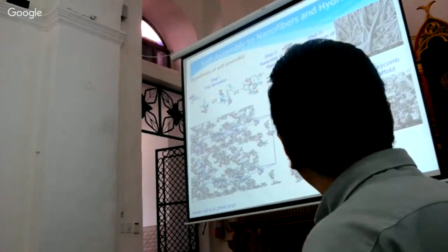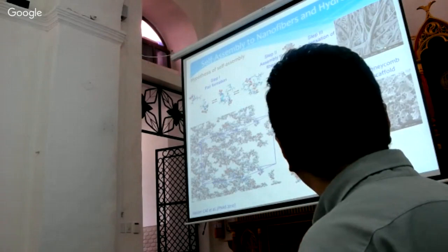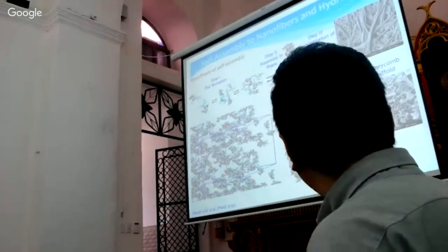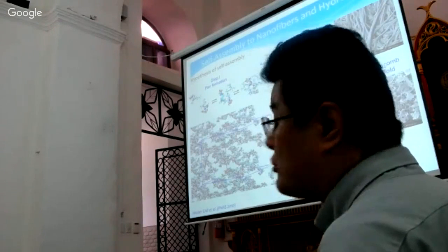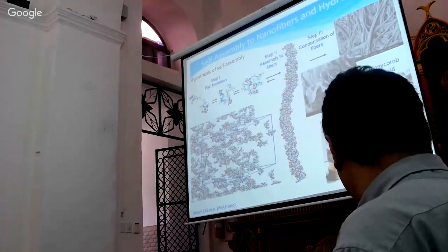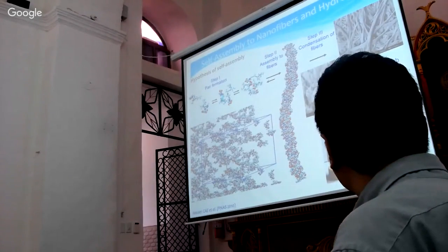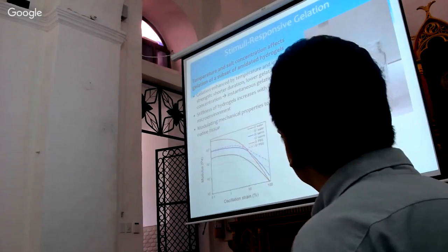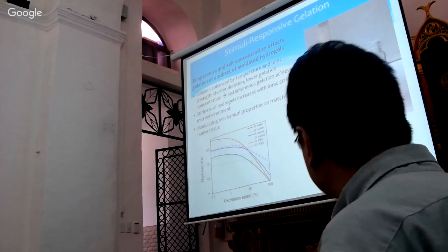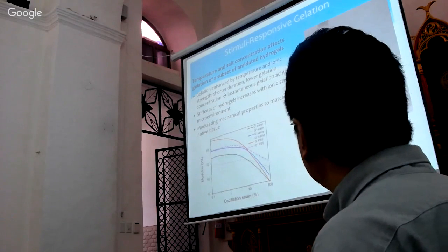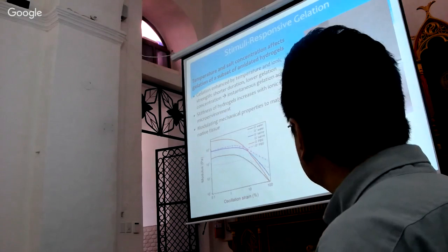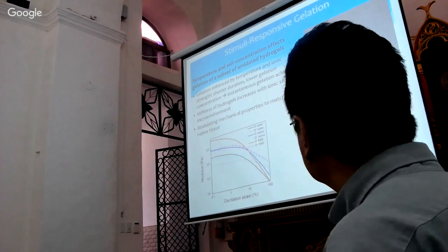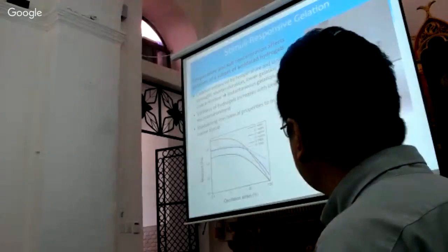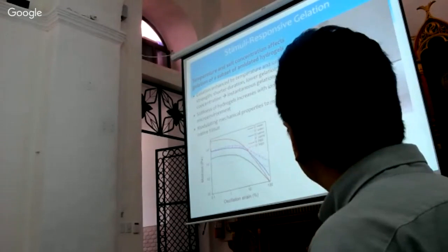And this is the scanning electron microscope picture showing the nanofiber. The dimension is only a few nanometers. And at larger scales you see a honeycomb scaffold structure. And by naked eye, you see that it's forming the hydrogel. This is also a stimulus-responsive hydrogel. That means if you change the dilution solution from water to saline to phosphate buffer, it can change the mechanical property of this material, and it gels almost instantly.